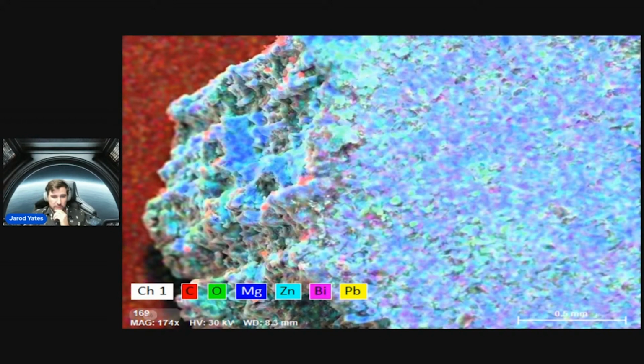Because it's a really thin layer of bismuth and we're turned to maximum brightness, maximum penetration depth of the light at 30 kV. You can see we got some oxidation going on. And specifically, there's a couple of spots here where you get a little bit of lead action going on. A little harder to see because it's so bright, but it's all there. Also, and this is going to be important in a little bit, these red spots of carbonization, you see those on the edge, specifically on the points. So something caused this thing to have carbon deposits occur at sharp edges, almost like it maybe was in a high voltage environment of some kind, potentially. Just throwing that out there.